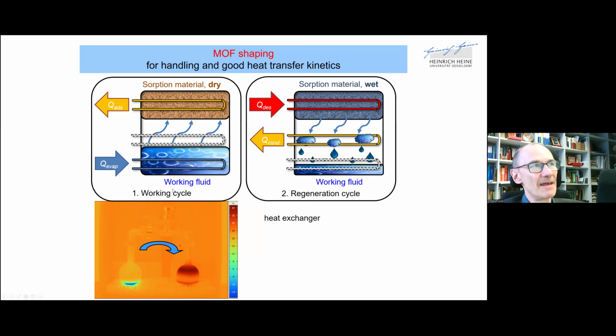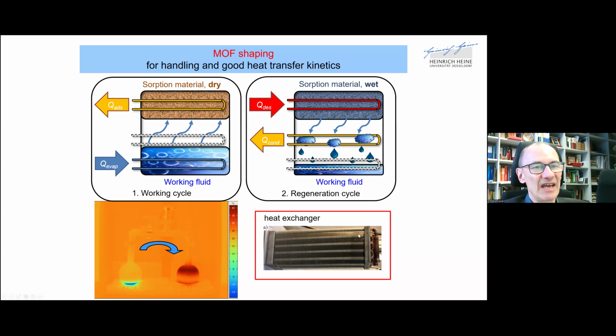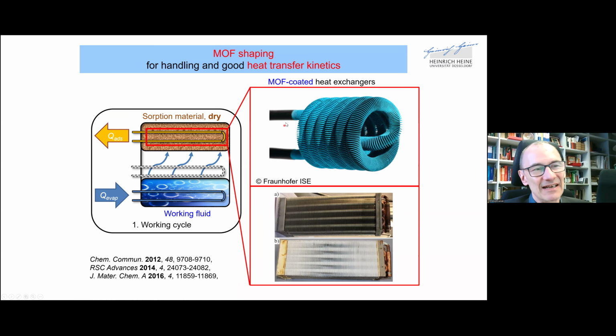Now, for this technology, you have to have adsorption material in close contact to a metal surface from which the heat of adsorption or the heat of desorption is dissipated or brought in. So that means we have to have a real heat exchanger, which then perhaps is filled with a MOF, or the MOF is then brought in between the lamellas of this heat exchanger, so that we have a device which dissipates the heat of adsorption and brings back in the heat of desorption as quickly as possible, at best with a thin layer of porous material only. So that is how it could be translated into a real world.